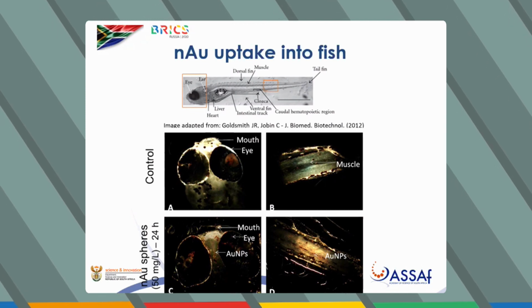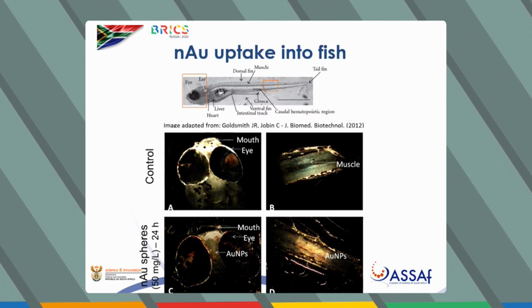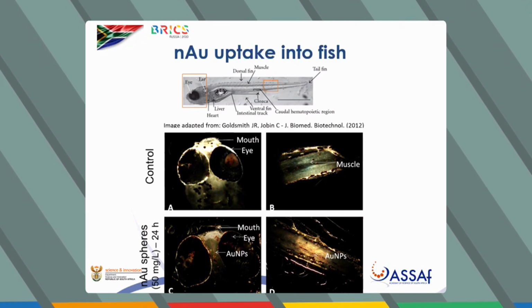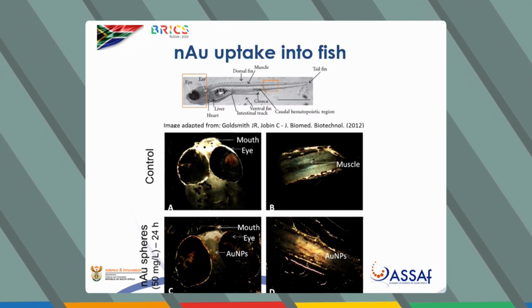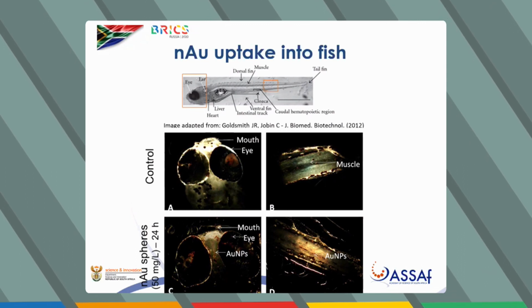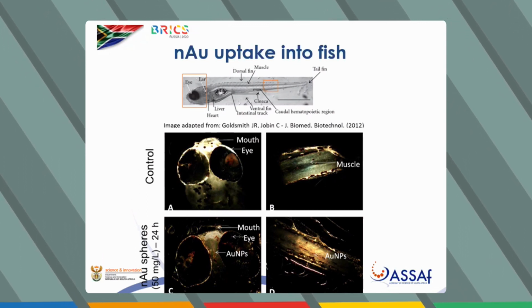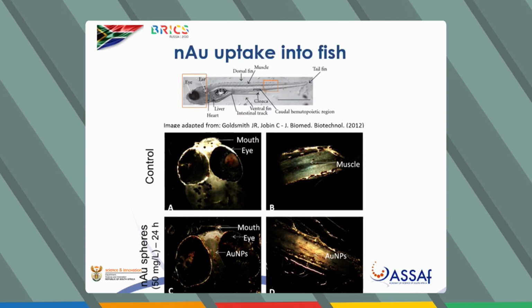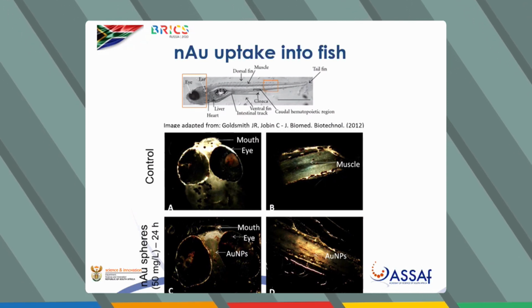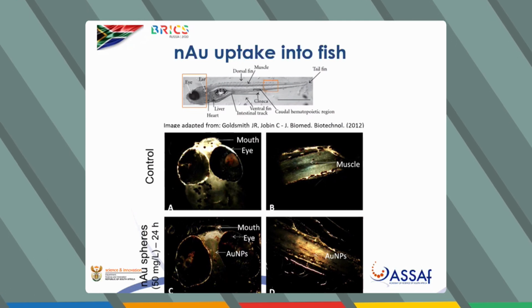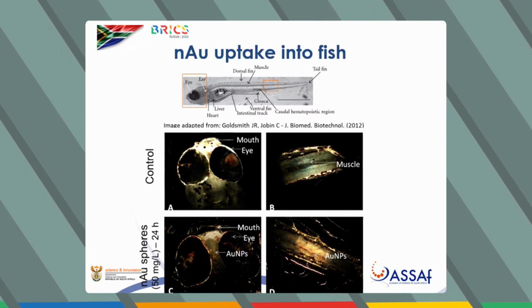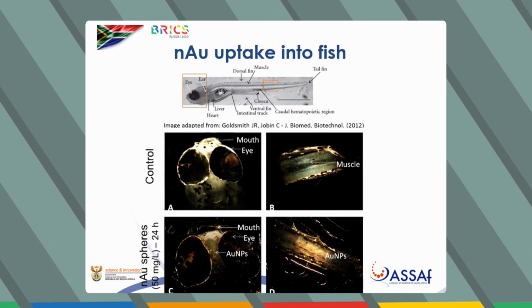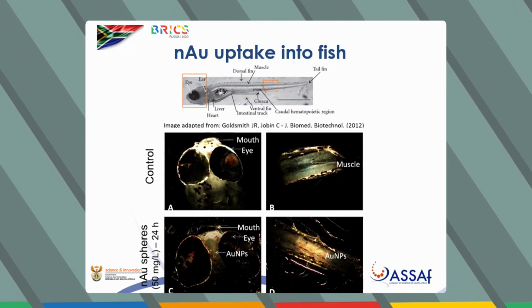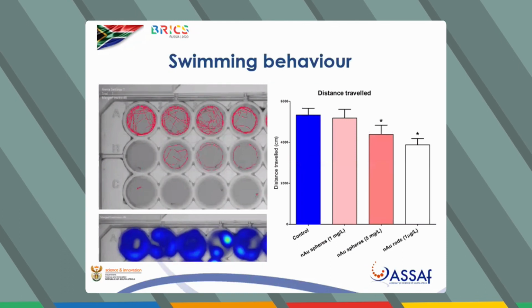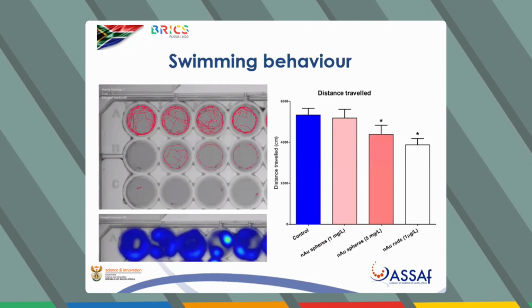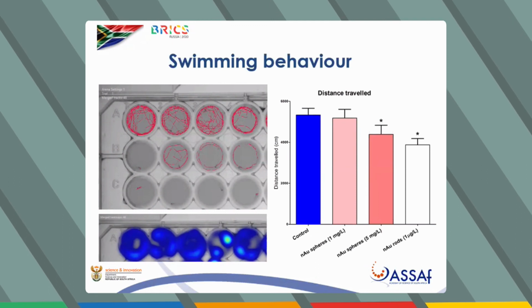We then also noticed something we had not seen in control. We did this with low concentrations and longer exposures, and we observed the same thing. We would have used about 2 milligrams per liter, and we actually saw gold nanomaterials in the muscle tissue. We performed a digestion of adult zebrafish to determine if it was just surface adhesion or in the muscle, and we were able to determine that it was in the muscle, and it seems to form little pockets.